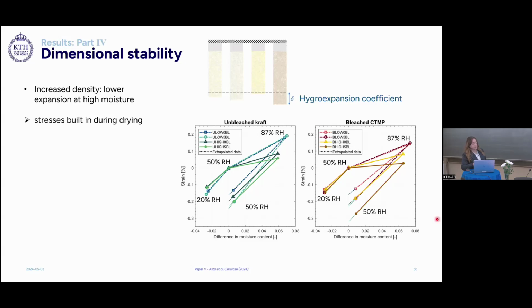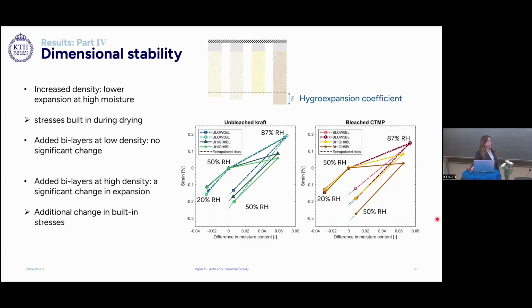We can see that with increased density, we have a lower expansion at high moisture, which means that the stresses are built in during drying. With the added bilayers at low density, there's no significant change. But with added bilayers at high density, there's a significant change in expansion, and this means that there's additional built-in stresses.